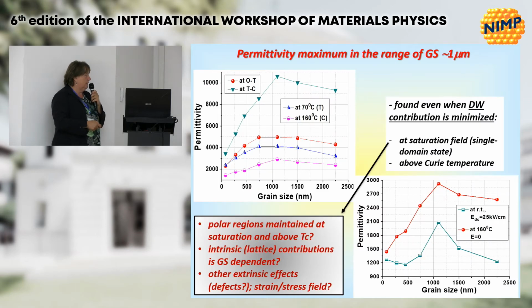Moreover, we found the existence of a peak even at high temperatures when the system should be cubic, so when we should not have domain walls. Maybe there are some reasons for this behavior that should be further checked, and maybe the intrinsic component is grain size dependent, or depends on some defects.